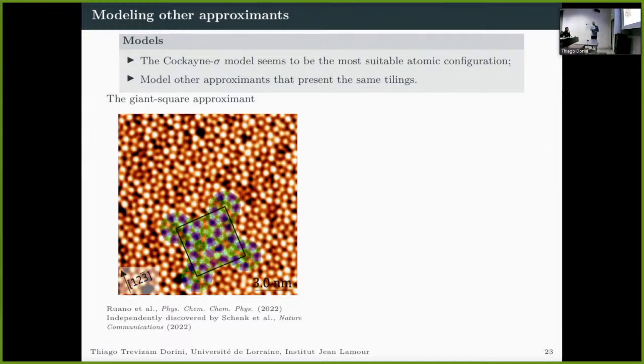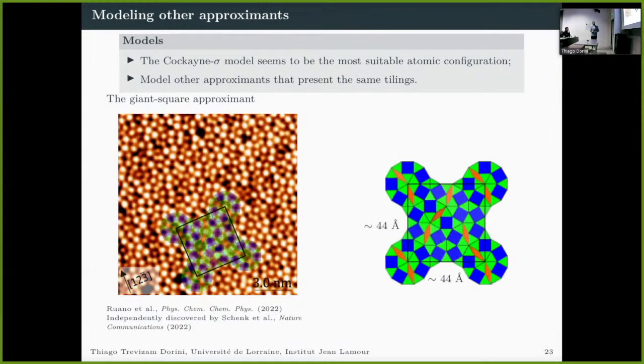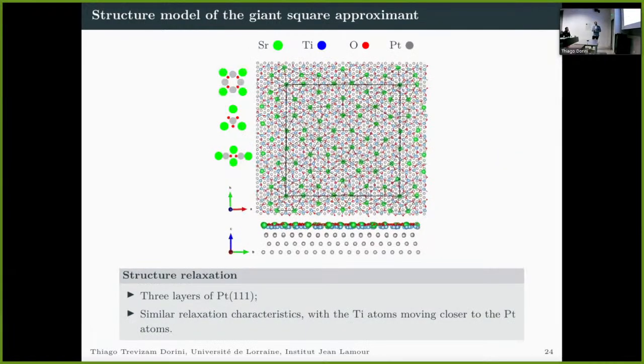And here we have the structure of this approximate phase, which is a giant square because it is a really big structure of 44 by 44 angstroms. And it presents the three tiny configurations, the square, triangles, and rhombuses. And when we use the model by Cockayne with these three tiny configurations, we can create this approximate structure. In this case, we have selected to model this structure with 3 layers of platinum due to its bigger size.